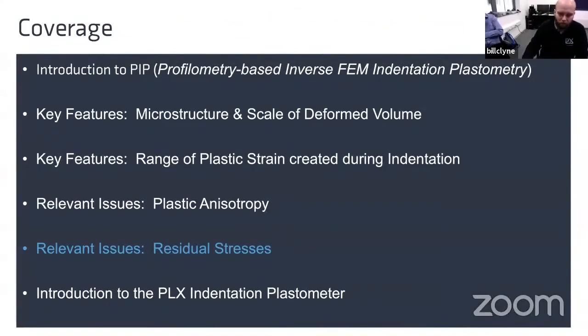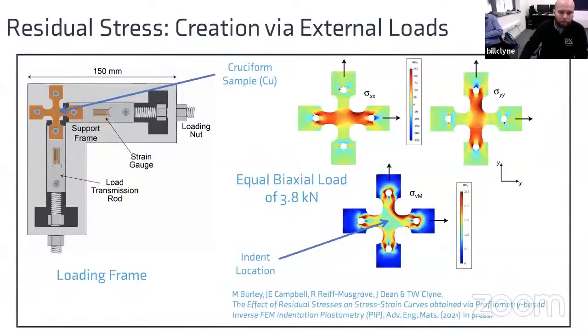Okay, so if we move on to residual stresses. The way that we investigated residual stress was using the rig shown on the left-hand side. It's quite difficult to generate residual stresses of a known or very accurate value, and so how we decided to do it was to apply the load to the sample.